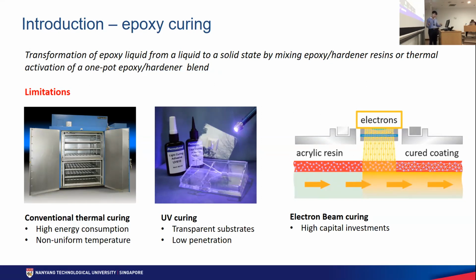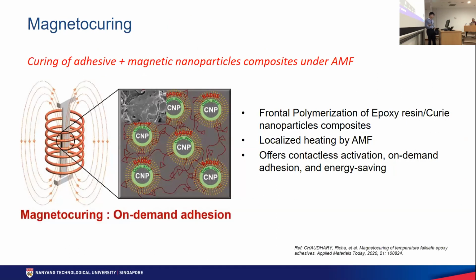Electron beam curing, because it has higher energy, can penetrate deeper into the surfaces and give us a more uniform curing profile, but the initial capital investment is very high. That's why we're developing this technology that involves induction curing, which in our group we call magneto curing. It's essentially the curing of adhesive and magnetic nanoparticle composites under an alternating magnetic field.